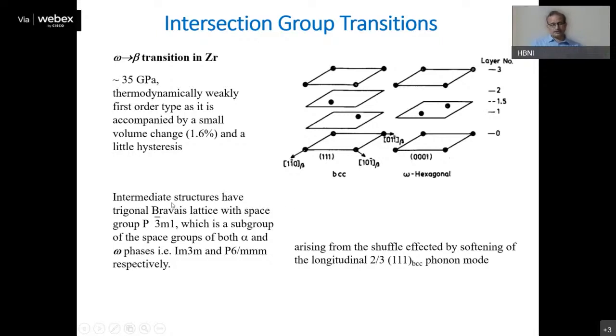So as we discussed earlier, in the case of this kind of phase transition, where the softening is happening because of some symmetry change, it should be related to some phonon mode, because it is a shuffle kind of thing. So there should be some phonon mode which softens and describes this phase transition. And indeed, from calculations, it has been shown there is a longitudinal 2/3 BCC phonon mode which actually softens across this phase transition.